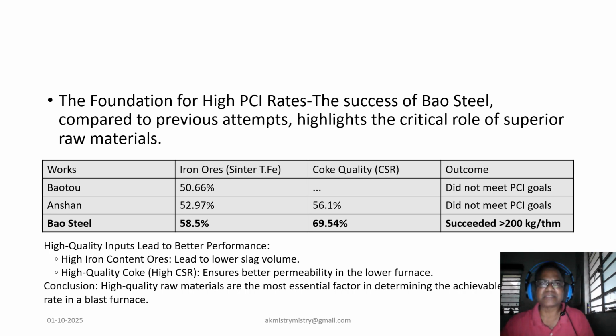As you can see in the table, Bao Steel used sinter with a much higher iron content, 58.5%, which leads to lower slag volume and better permeability. Even more critically, their coke quality, measured by coke strength after reaction, or CSR, was significantly higher at 69.54%. High quality coke maintains its integrity inside the furnace, ensuring the coke bed remains permeable.